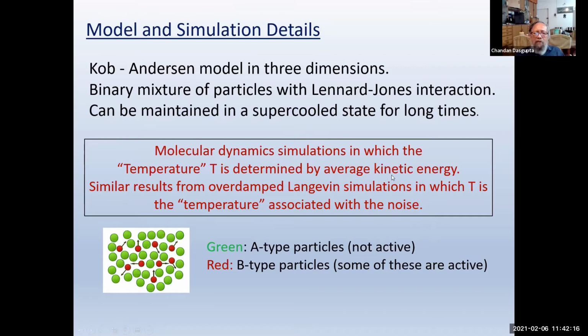And then the first thing that we did was basically a simulation. We did either molecular dynamics simulation or Langevin simulation. In both cases, we get essentially the same things. So again, I'll skip the details of the simulation. It's basically looking at the dynamics of the system once you specify all the parameters. So this is a sketch of the system that we are looking at. The green particles are A-type particles and the red are B-type particles. We have a binary mixture. And in the first model that we did, we give activity only to the B-type particles. So then one can simulate the collective behavior of the system at different temperatures. Keep the density fixed at a high value and change the temperature.